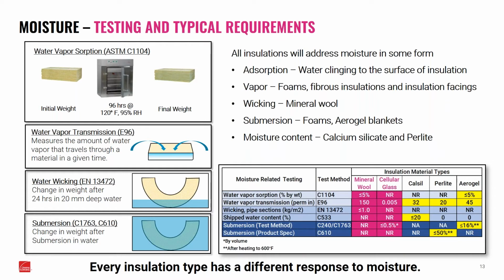You look at water vapor sorption; those are going to be more around fibrous insulations. Water vapor transmission, again, isn't typically tested, although cellular glass is going to have that in its spec because that is one of the properties that is most important with that product. And just to point out the two extremes, you have mineral wool, which is very vapor open, versus cellular glass, which is very vapor closed, which makes it a great product for use in cryogenic and cold applications. If you look at calcium silicate and aerogel, they're still considered to be vapor open, although maybe not as vapor open as mineral wool, but they will allow water vapor to pass through those products.